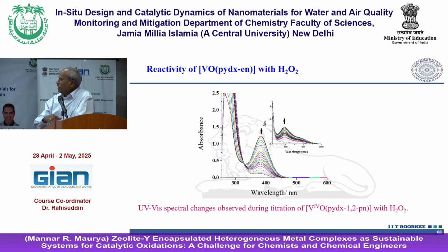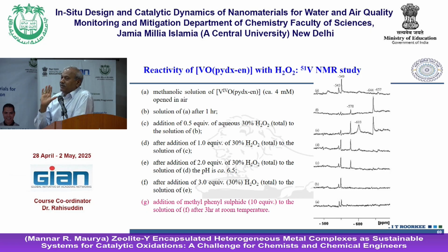Now here, to give the reaction mechanism, we have used the homogeneous complex and studied the effect by vanadium NMR. Now, this is a vanadium 4 compound, which is NMR inactive in general. So in the beginning, what is recorded is after keeping the sample in solution for several hours, so that oxygen has entered and converted it into vanadium 5. So two peaks are seen, and there is also the possibility that it is oxidizing, and since this is done in DMSO, partly DMSO can coordinate to the metal center. So partly DMSO coordinated and the pure metal, two peaks are seen there. When you further add H2O2, the peaks get better and better, and another peak you can see is due to the formation of the peroxo compound.